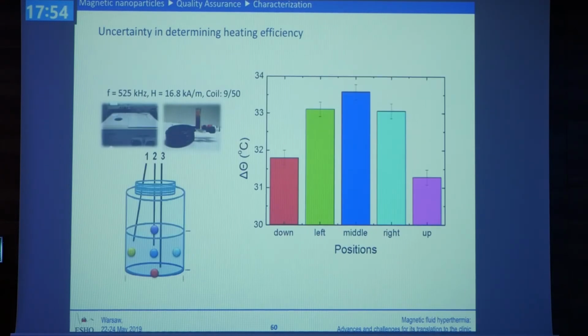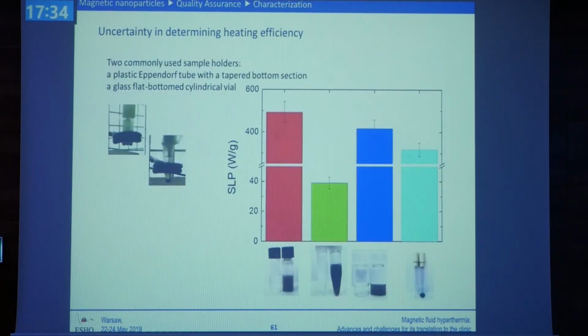Do you measure in the middle of the vial? Do you measure on the end points? So you can see that for different positions inside the very small vial, which contains only 1 milliliter of a dispersion, you have different temperature rises inside your vial. So you have to know also where you are measuring. And of course, also the vial plays a role.